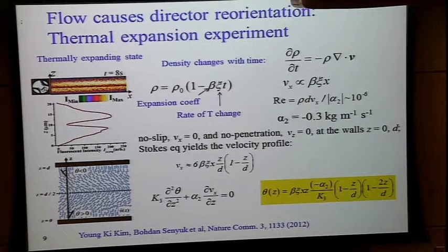So it's an interesting result, because if you thermally expand, for example, water, nothing interesting happens most of the time. If you thermally expand a solid, it's the same lattice before and after, just a bigger period. But in the liquid crystal, you have this non-trivial transformation in the director field that again illustrates that flow and the gradients of velocities can realign the director.